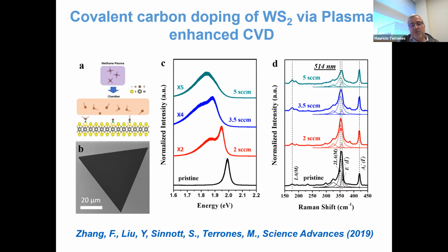As we introduce more carbon, we can see that the E prime is again reducing in intensity, so the ratio is changed compared to the A1 prime. This is when you have more carbon in the system. What is happening as well is that the gap is changing. So you again reduce the band gap, and then we get this hump, which could be related to defects.